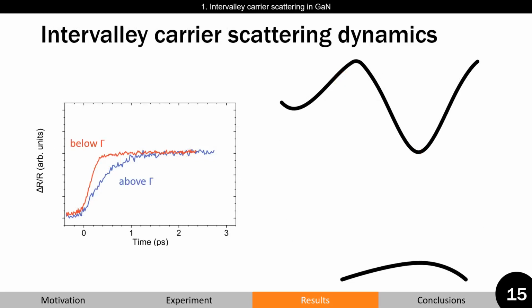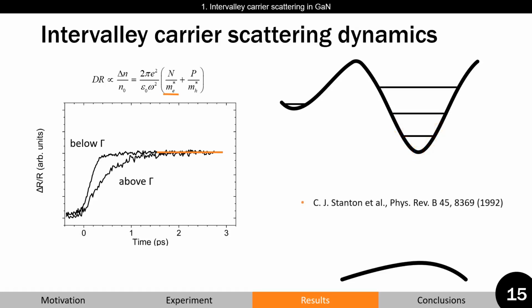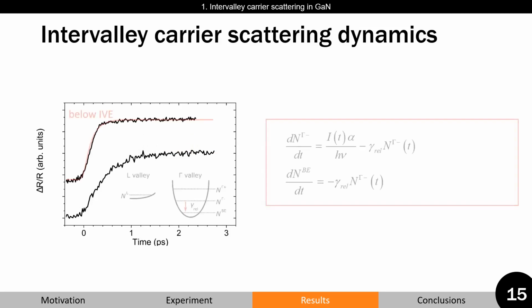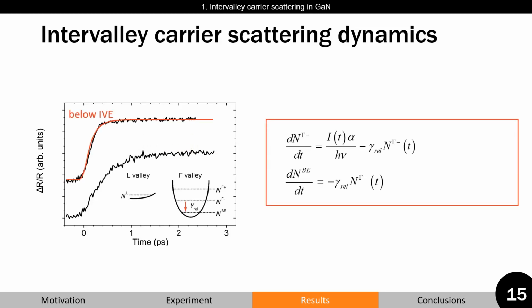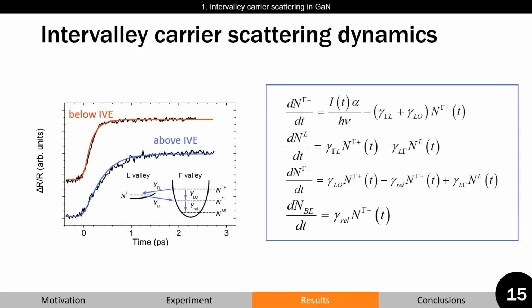In short, differential reflection signal is inversely proportional to electron mass. In other words, at longer times, the signal tells us that all electrons relax at the bottom of the conduction band, where the effective mass is the lowest. Then, we can describe our system with discrete energy levels, and using a system of rate equations, model the experimental data. For transients below intervalley energy, phonon relaxation rates are evaluated. For transients above the threshold value, intervalley scattering rates are determined.